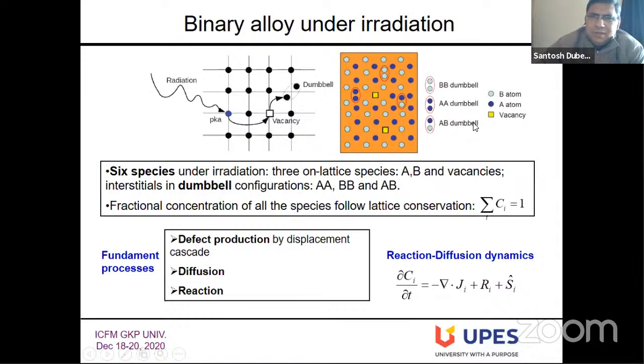So if you want to understand the fate of the material under irradiation, you need to track all these species. What is happening with what? You have defects like interstitials and vacancies, so there is a possibility of reactions of the defects with the vacancies. Defects can also react with the atoms. In fact, there are three different fundamental processes that we need to track. One is defect production: how the displacement cascade, how the fundamental interaction of the radiation or the fission fragments with the material, leads to the displacement cascade or to the production of a residual amount of defects. And then how these defects diffuse. These defects diffuse via atoms on the lattice, and then how these species react.